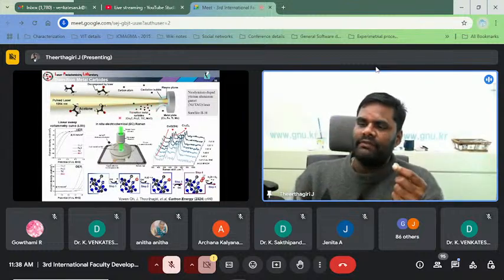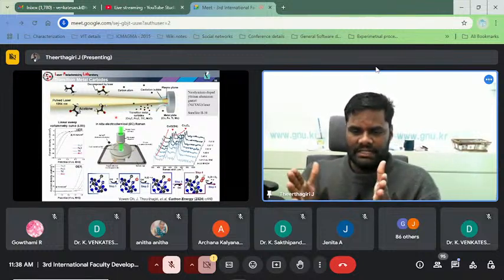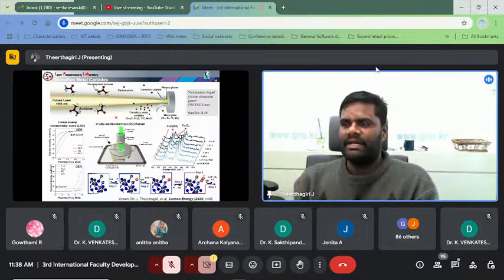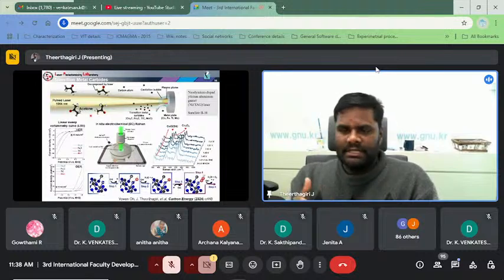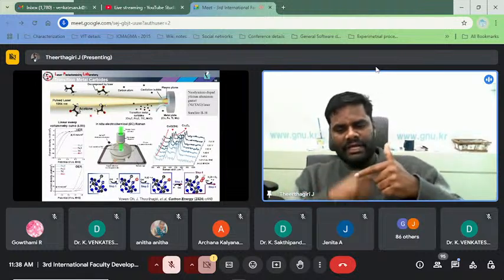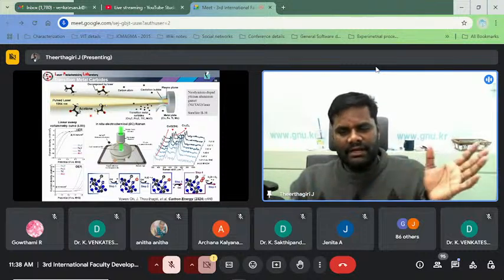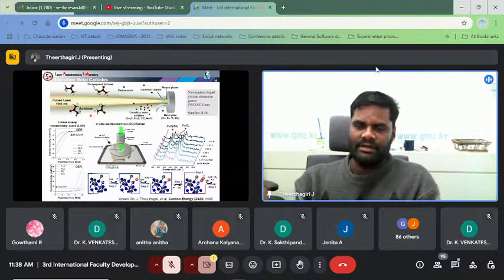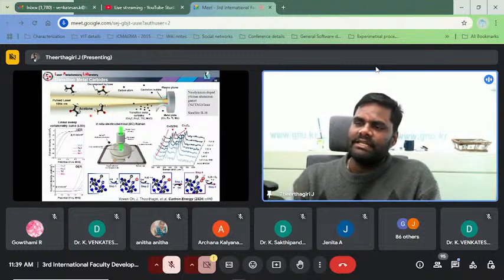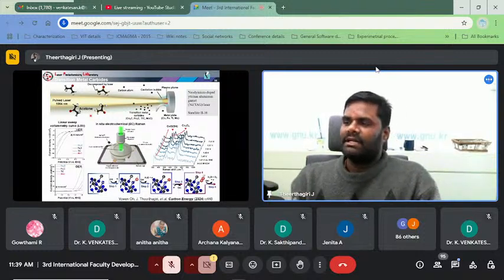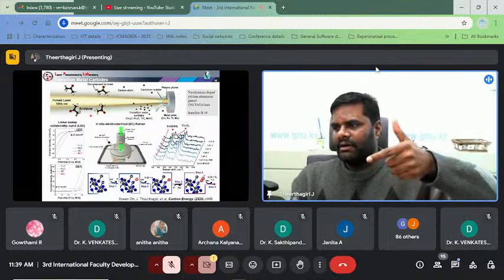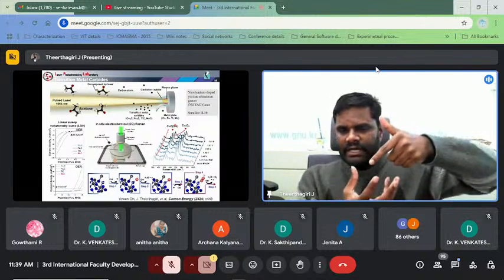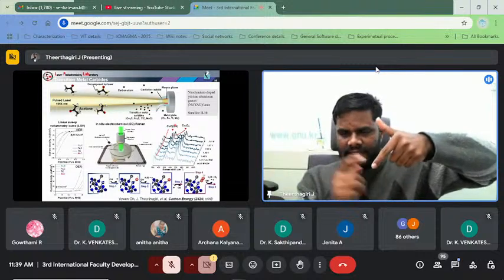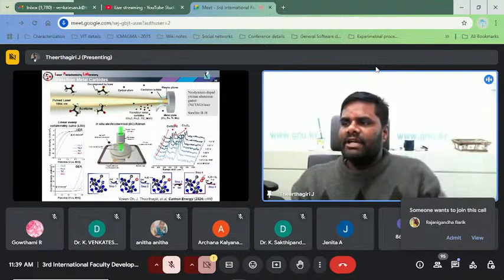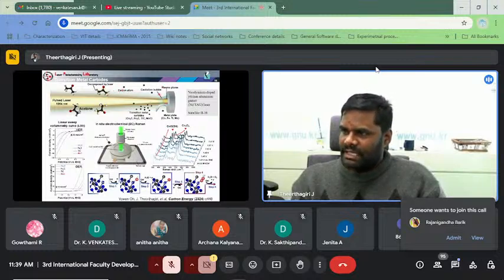If required, we change to a different carbon chain solvent. In acetone, methanol, or ethanol, it can form a graphitic carbon layer also. There are n number of studies which we are performing. But in this reaction, we took an acetone solvent, with target metal plates dipped in the acetone solvent, and we pass the laser. The acetone decomposes and produces various carbon fragments. So this is the mechanism.